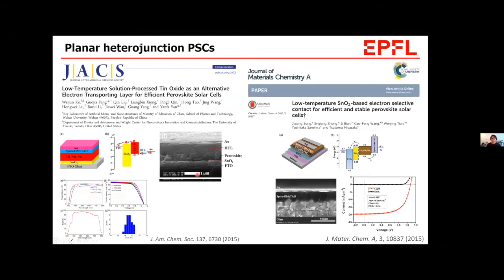So here, these works are about planar heterojunction perovskite solar cells based on the low temperature solution processed tin oxide as an ETL. I mean, the low temperature is like less than 200 degrees C or 150 degrees C, so it does not harm the flexible substrate. And they prove that the low temperature processed tin oxide is an excellent alternative ETL material. And as I said, this is compatible with flexible substrate and the roll-to-roll manufacturing process as well.